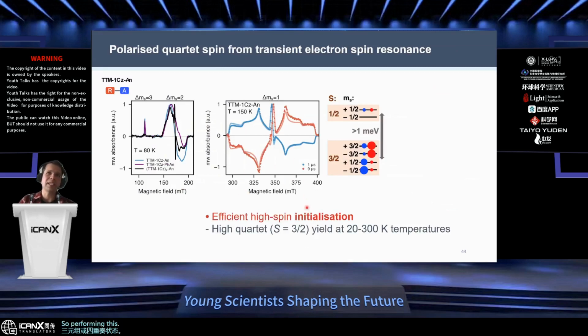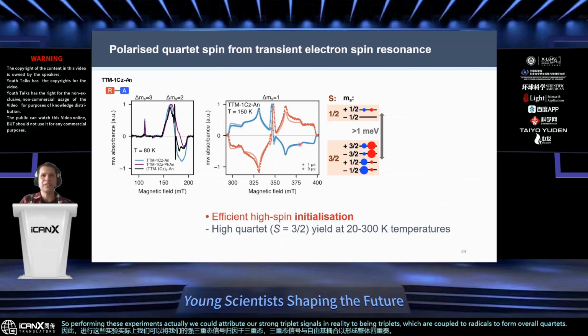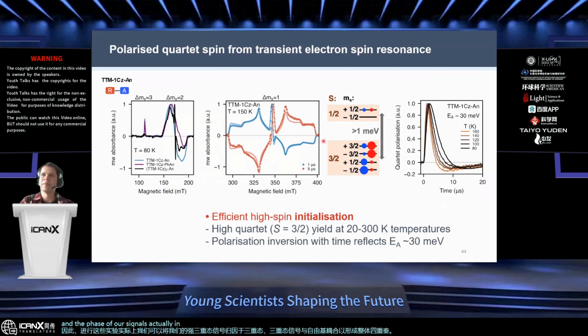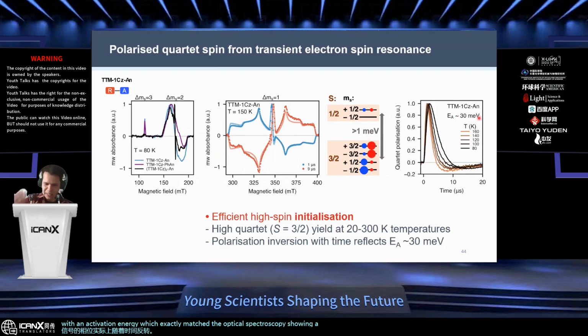So performing these experiments, we could attribute our strong triplet signals in reality to being triplets which are coupled to radicals to form overall quartet states. And the phase of our signals actually inverted with time with an activation energy which exactly matched the optical spectroscopy, showing us that these magnetic properties were directly related to the optical properties that we saw in the system.